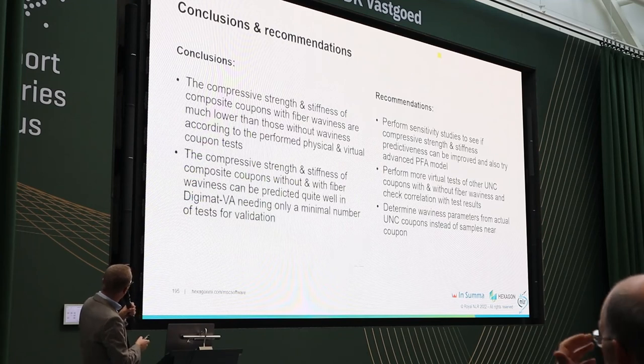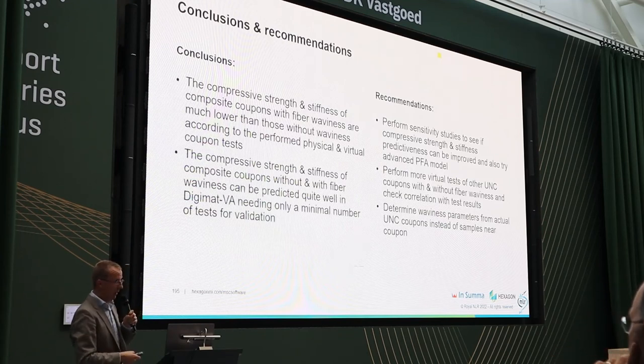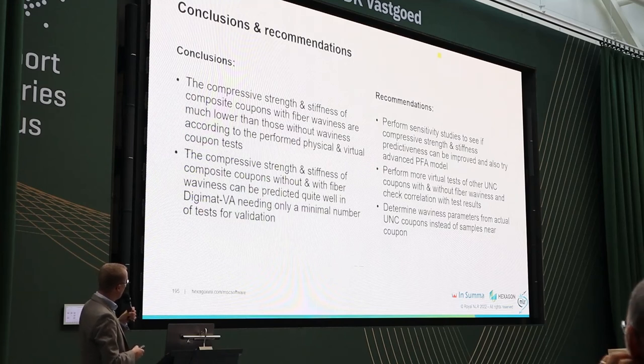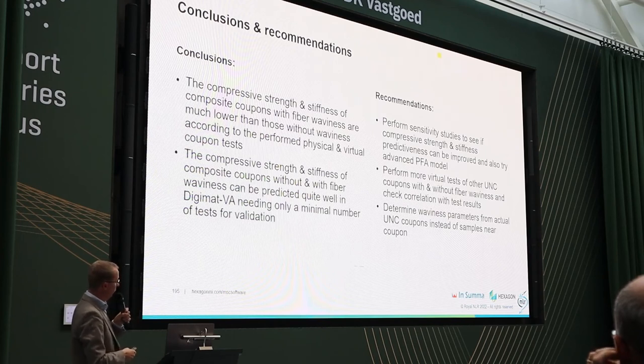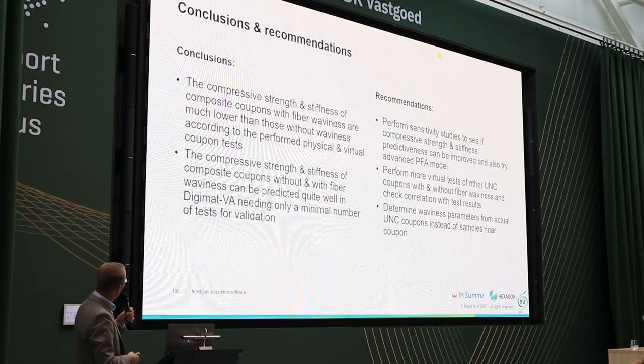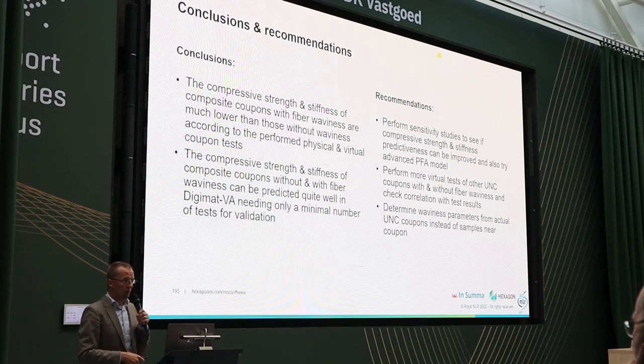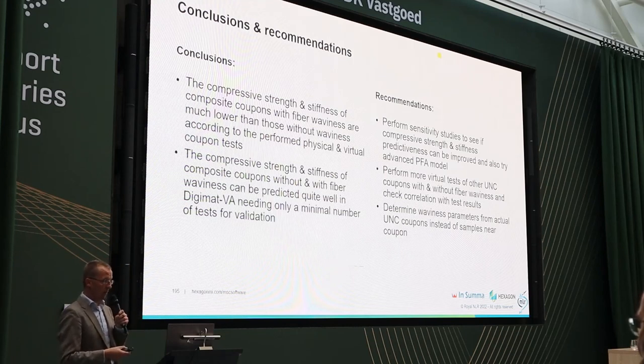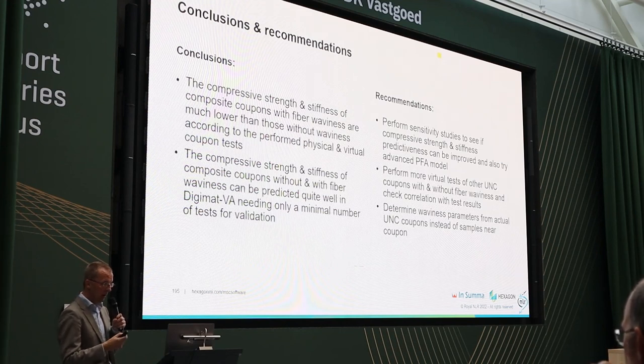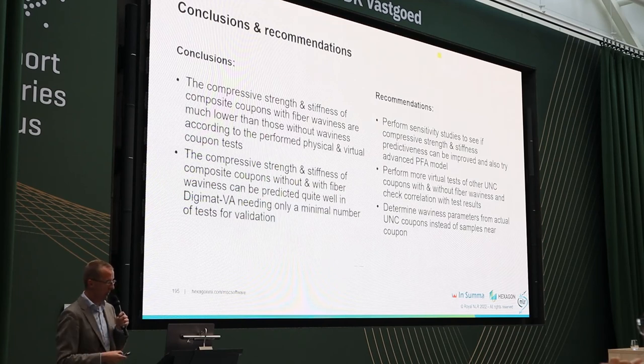Next slide, some conclusions. I can predict quite well the compressive strength and stiffness with fiber waviness. Also, there is a large reduction in stiffness and strength compared to the coupons without waviness. So that's quite nice. And also, I didn't need a lot of physical testing to determine the ply properties, which is quite nice about the Digimat software. If you're lucky, you have the qualification data already available. So it's a strong point, I think.